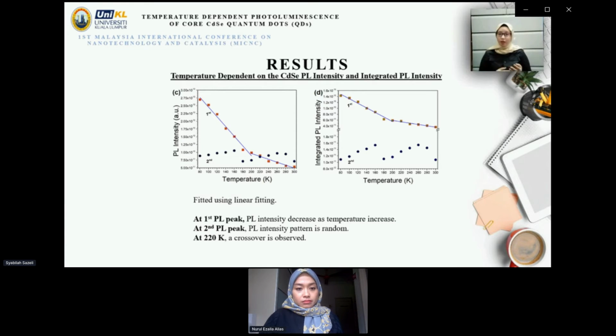Yet, at the second peak, the pattern observed is random. It also can be seen at temperature 220 Kelvin. There is a crossover between first PL intensity and second PL intensity. For the figure of PL integrated intensity versus temperature, the trend is approximately similar to the figure of PL intensity versus temperature.